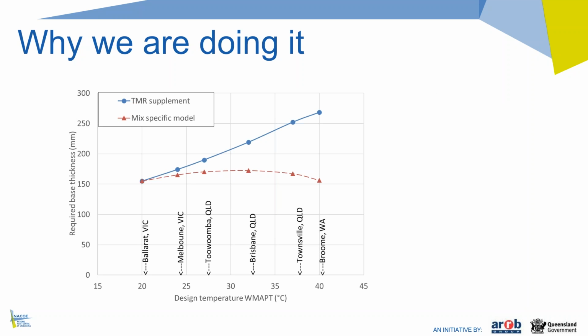And this is another slide on why we were doing that. Actually, the whole reason why we started this project is because according to the current Austroads design method, as the temperature goes up, you need more asphalt to get the same fatigue performance. This graph shows the design thicknesses for a certain design situation using the TMR supplement, so that's the continuous line, at different temperatures. And you will see that in Brisbane you will need a thicker pavement than in Melbourne to carry the same traffic if you use the current TMR supplement.